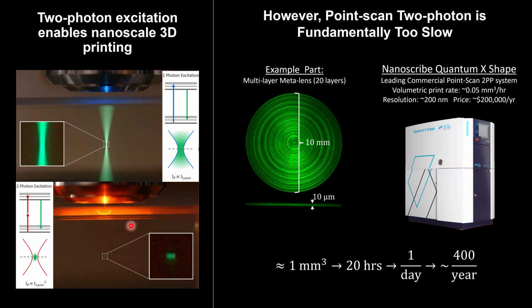So if you think about an example part you might want to make, this is a lens that's about 1 centimeter in diameter, 10 microns thick, so still a very, very sort of thin lens. Making this using a system like the Nanoscribe Quantum X, this has a volumetric print rate of about 0.05 cubic millimeters per hour at its highest resolution of about 200 nanometers laterally. And so this component is about 1 cubic millimeter, which means it would take about 20 hours. So you could make about one of these per day or about 400 per year. This is fine for sort of academic R&D settings, which is typically where these are used, but not very practical for actual sort of industrial use.